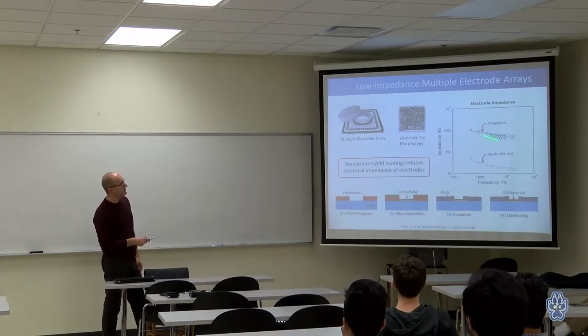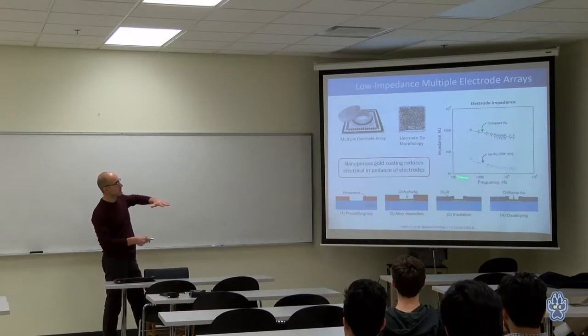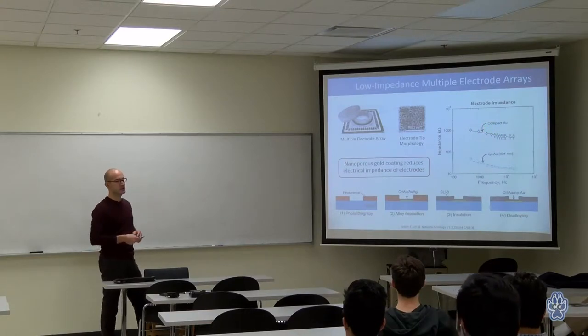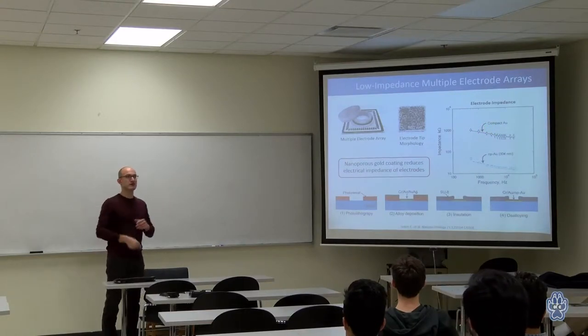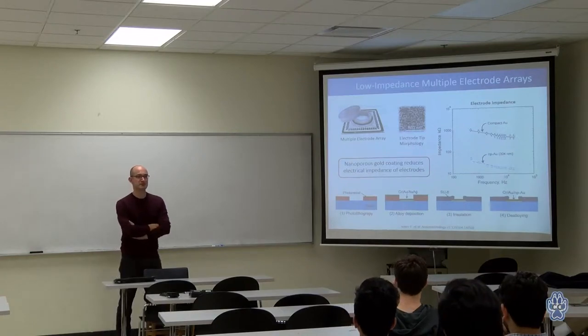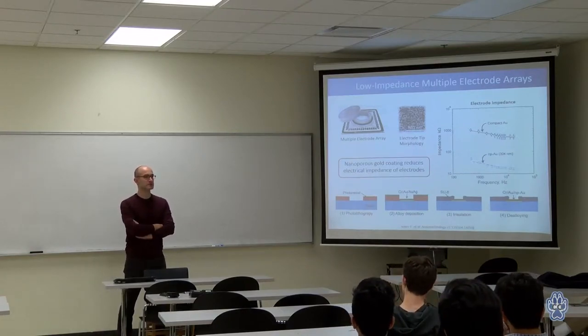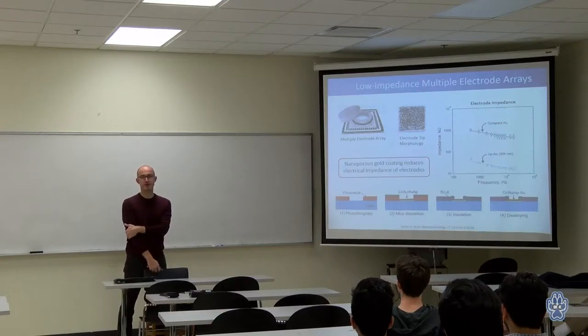And you can see that compared to a flat gold electrode, with the nanoporous gold we basically reduce the electrical impedance. Do you have any thoughts on why the impedance would go down for a porous structure? It's the same size, but it's porous compared to planar gold. More surface area? More surface area.